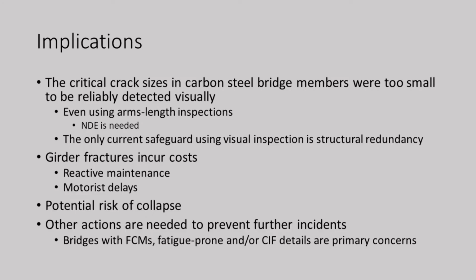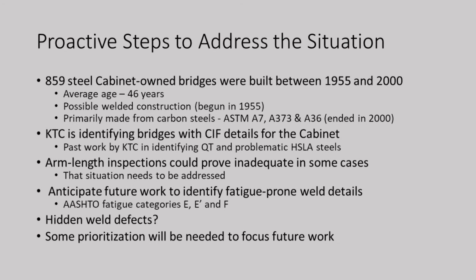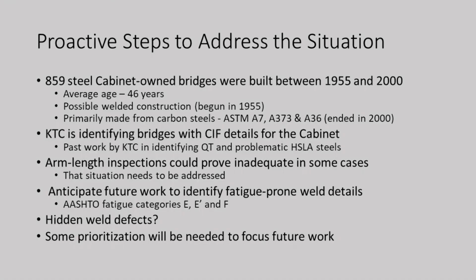Other actions are going to be needed to prevent further incidents like we've seen. Our concern, firstly, probably goes to bridges with fracture critical members, and secondarily, those with fatigue-prone or CIF details. For Kentucky, we foresee some proactive steps to address the situation. First thing you got to do is look at your inventory. We have 859 steel bridges that were built between 1955 and 2000 that are of concern. And the question is, why those dates? 1955 is when Kentucky started using welding. We haven't seen this issue with riveted bridges, just welded bridges. And right at 2000, by policy, the cabinet quit using A36 steel and went over to grade 50 steel exclusively. So this is the time interval and the number of bridges that potentially qualify as bridges of concern.